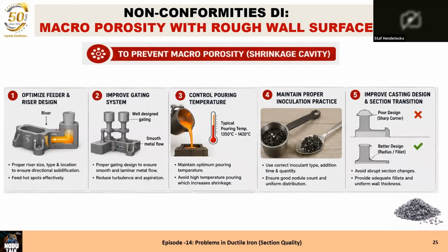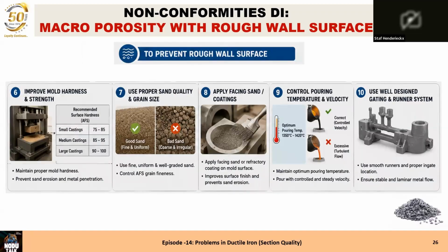And of course, the casting design: you have to discuss with the customer that there are no abrupt section changes, and that the wall thickness differences from one section to another are smooth and not brusque. Mold hardness: you must make sure that it's strong enough, and that means mainly for green sand you must be assured that the sand is rammed properly. But also in chemically bonded sand, there can be areas that are a little bit difficult to reach, and there the sand is then less good than in other areas, and this can cause problems. Proper sand quality and grain size of the sand decide the strength of the sand without any problem. Facing the coating, the thickness of the coating must be adapted to the thickness of the casting, and it must be applied properly.